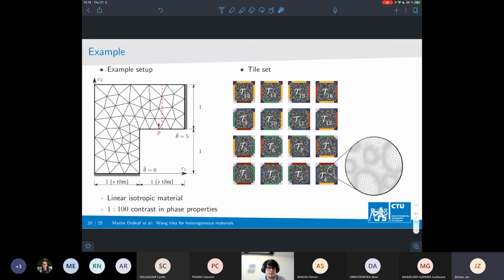So how this works is something I would like to show on this example I mentioned before. Here you can see what is the fineness of the finite element mesh, which is used in obtaining this fully resolved solution. So we really would like to make sure that the reference is rather accurate. And there are two additional parameters I will need later on. One is P, which says what are the local coordinates along this section, in which I will have a look at local solution profile. An additional parameter is this small s, which says what is the number of tiles which I fit into this region. So it actually sets the scale separation of my problem. And this is run for linear isotropic material and with quite large contrast in phase properties.